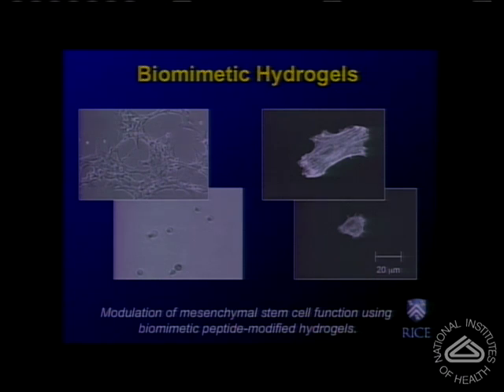Also, what we and others have found over the years using such biomimetic materials is that one can control the spreading and differentiation of progenitor cells by simply varying the ligand concentration on the surface or the ligand composition, again, in an effort to use biomaterials as a platform to control the differentiation of progenitor cells.